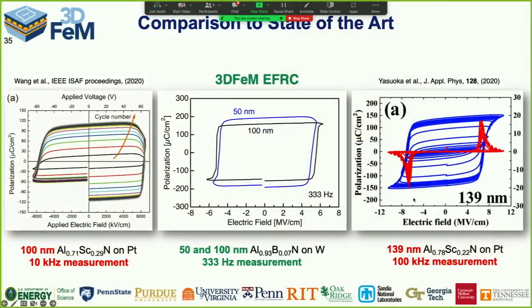Looks much nicer looking hysteresis loop, but they've gone even an order of magnitude higher in frequency to hide some of its defects. And that's because when you add scandium to aluminum nitride, the band gap comes down really fast. And so it's not that they've grown bad films, they've grown amazing quality films, but it's just really hard to keep the material insulating enough at 6 megavolts per centimeter to avoid leakage currents.